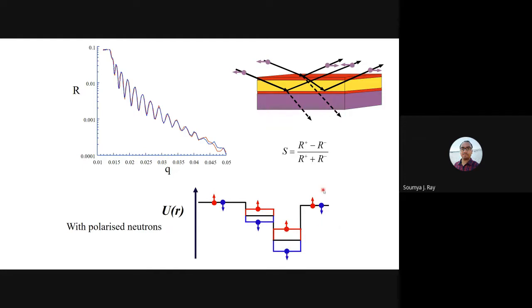So as a result, since the up and down spin neutrons experience a different magnetic, or overall, potential, that will be reflected in the final reflectivity. So you will get a particular reflectivity pattern corresponding to the spin up state, and another corresponding to the spin down state. And from there you can estimate something called the spin asymmetry. And if you do a little bit of modeling, the same thing you have to do for X-ray reflectivity also, then you can find out how the interfaces behave magnetically, and if there are any buried magnetic interfaces, etc.